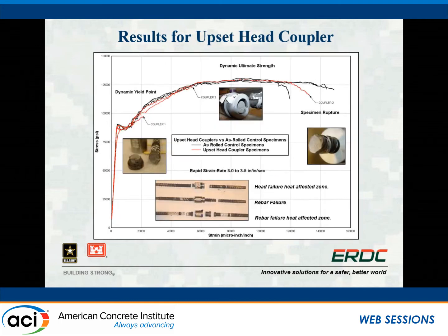For the upset head coupler, most of these test results achieved similar tensile strengths, but the ductilities varied significantly, and in many cases they were not acceptable. If we look at the failure surfaces, most of them are also associated with the coupler itself. In one case we do get the ideal failure, that's this last curve here. The ideal failure is that you get the same tensile strength and same ductility as the control samples. But in many cases we saw the influence of the coupler, especially heat affected zones near the coupler, jeopardizing the strength and ductility of the bar.